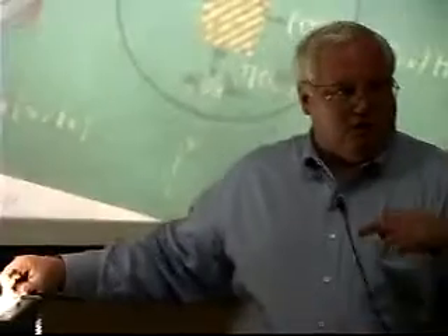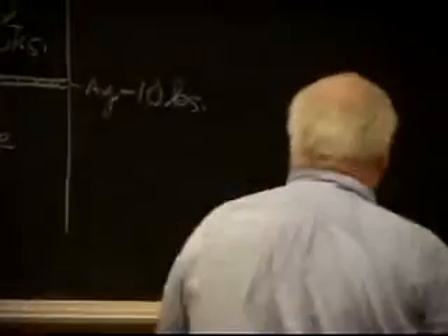Eventually, the strength goes back down, and that's because of defects. When you start getting joints that are less than a tenth of a thousandth, you're talking now less than a few microns, less than 5 microns in thickness, you're getting into surface roughness problems and defects in incomplete joints. So this is back down to defects. This is basically contact strengthening in here when you are at these thicker joints, but it's still fairly thin. 10 thousandths was the high end of that. 10 thousandths, yeah, 0.01, 1/100th of an inch.